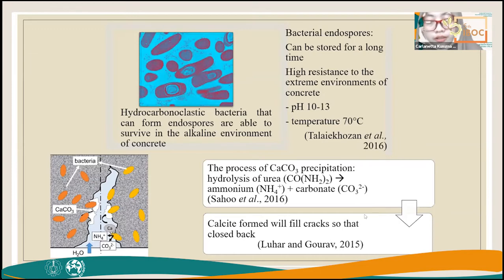In bioconcrete that contains hydrocarbonoclastic bacteria, if there is a crack, water and oxygen will enter and activate the spores, which could trigger the formation of calcite through the enzymatic urease mechanism. The calcite formed will fill the crack so the crack will close back.